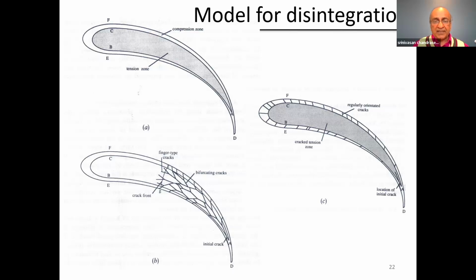Then each of the split cracks picks up speed after feeding in energy from this tension zone. They reach the threshold speed, they bifurcate. So what happens is one crack leads to 2, 4, 6, 8. The process repeats ad infinitum. And as a consequence, the whole drop becomes powder.